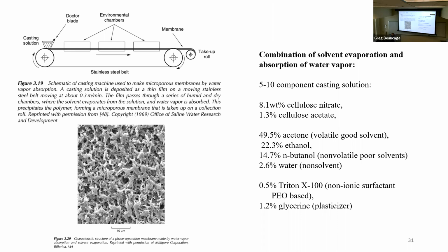And then this is a process where you start with a polymer and a solvent, then you put it into just a humidity chamber. So you don't dump it into a bucket of water. The water in that case diffuses through the surface. You get phase separation at the surface. So you can get a spinodal at the surface and some kind of coarser grain structure internal. Right, so this environmental chamber is used because it's easier to get a gradient and kind of control it in the process.